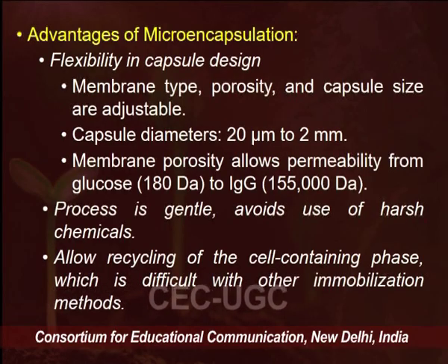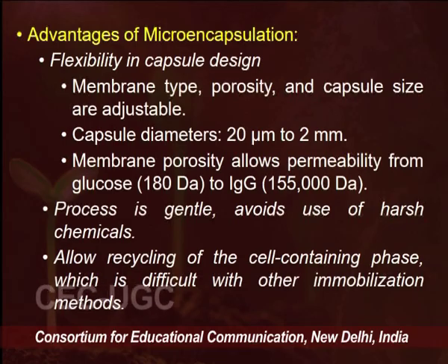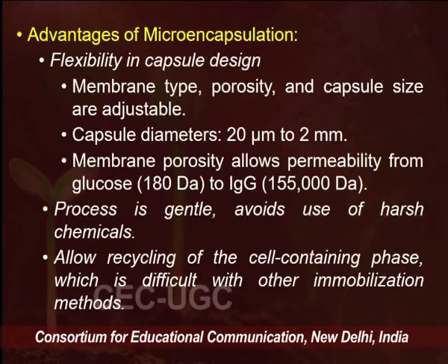Because different membranes are available that will help in forming capsules of size ranging from 20 micrometers to 2 millimeters. Similarly, membranes are available which have a porosity range from small molecules like glucose to a very large macromolecule like immunoglobulin G, having a molecular weight of 155,000 Daltons.